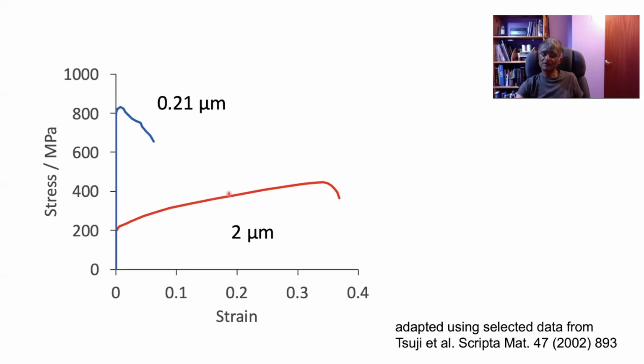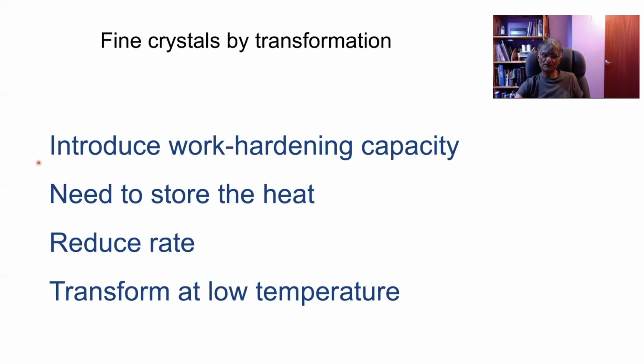Here, when the grain is large, you have the dislocations moving about inside the grains, and therefore you delay your plastic instability by work hardening. But at fine grain sizes, you lose that ability, and therefore you get an early plastic instability. So the fourth condition is that we must have a mechanism of introducing a work hardening capacity. Now, at this point in the lecture, I ask the students, how would you increase the work hardening capacity? Because we've done it already.